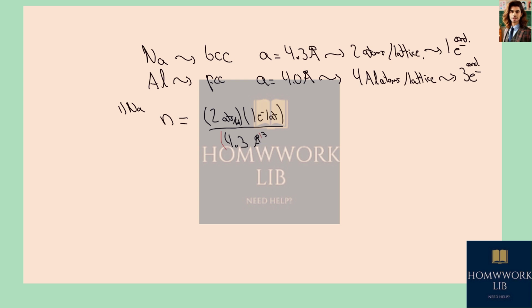Of course, here, in order to simplify our result and to not do a lot of conversion factors, let's do it directly in meters. So this is going to be 4.3 times 10 to the minus 10 meters, and this value cubed. So the result that we get from this is going to be 2.52 times 10 to the 28 meters to the minus 3.